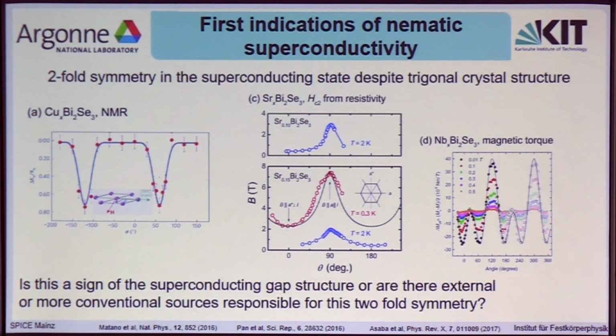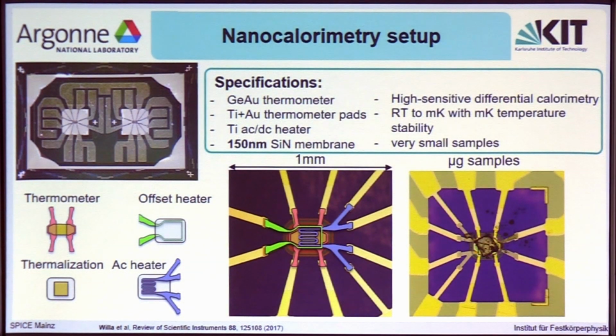Okay, so as most of my measurements are done in specific heat, I want to start with introducing you to the setup that I was using at Argonne. So the specific heat setup that I built there is based on silicon nitride membranes. That means we take a silicon wafer, we coat it with silicon nitride. The silicon itself is later back-etched, leaving only a 150 nanometer thin transparent membrane suspended over a 1 millimeter square window. The active layers that we need for specific heat measurements are then deposited by photolithography in the center of the membrane. You can see a microscopic image here.